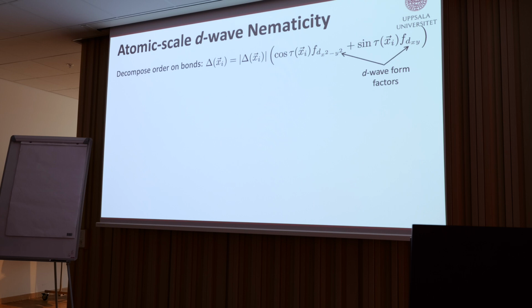So I can go and see what the individual order parameters are doing. I can decompose the order parameter into the different individual d waveforms. So you have dx squared minus y squared and dxy. This was an S component, if you remember. The S component is essentially 0, so I'm not going to plot it, but we did calculate it, but it does not show up. So I can just decompose this on each bond, on each atom. I can look at what is the local d-wave symmetry, and I can technically plot this by just forming a vector field for the d-wave order.